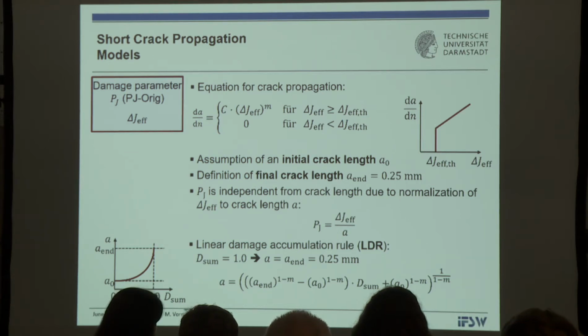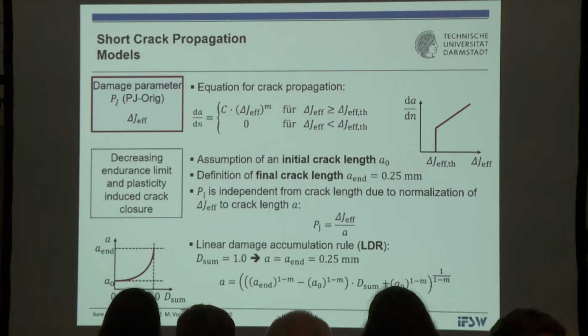And one extension is related to the threshold behavior. We do introduce the threshold in J, and we decide whether a cycle appearing provides a ΔJ which is larger than the threshold; then it contributes to damage and crack growth, and if it's smaller, it does not. This means that with increasing crack length and damage, the endurance limit of the material and the component is continuously decreasing.